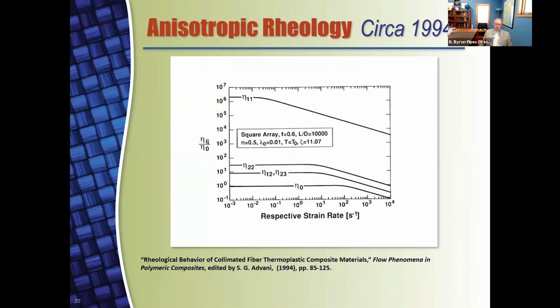If you take those equations and plot them, this happens to be for a specific polymer with a length to diameter ratio of 10,000. And you'll note that the eta 1,1, the viscosity in the elongational direction, is measured in the 10 to the 6th level, whereas the shearing viscosities are 10 to the 1st. The second elongational viscosity is a bit larger, but not much. So all of the other viscosities are relatively near that of the polymer, but the extensional viscosity is enormous, which gives some really interesting challenges in modeling flow with this class of materials, what we are now calling hyper concentrated systems.